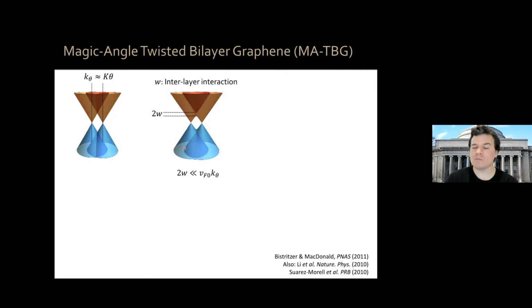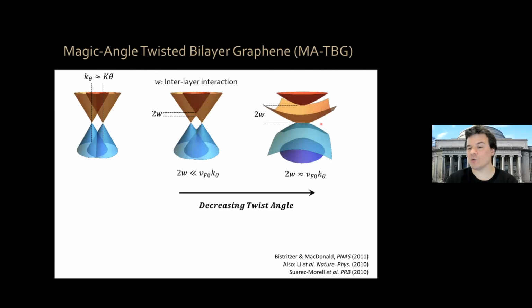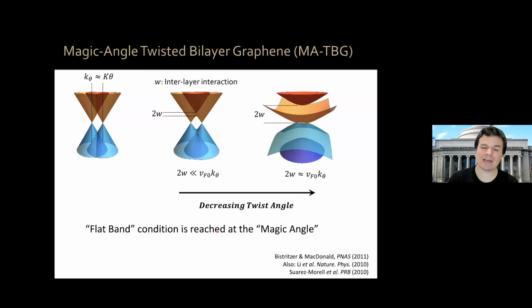Now this is the situation when this interlayer interaction is much smaller than the energy of that crossing point. But if we twist now towards smaller and smaller angles, these 2 points get closer and closer, and this lower band gets pushed down to lower and lower energy until it touches 0. Okay, that touching of 0, we say that a flat band condition has been reached, and that occurs at an angle called the magic angle. Okay, and that magic angle is 1.1 degrees. There was theoretical work about a decade ago which predicted this magic angle of 1.1 degrees. Okay, and that's for graphene on graphene. Different materials have different angles.